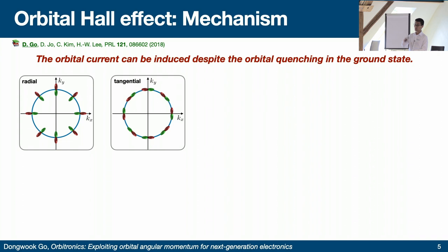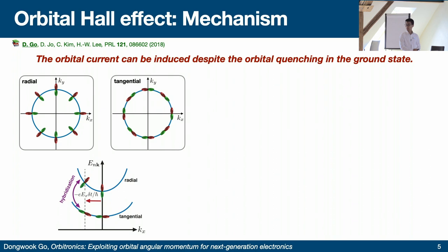The main starting point was that when there is a crystal field, it does not simply split orbitals in a rigid way. For px and py orbitals, the splitting depends on the crystal momentum k. Depending on the band, for p-orbital systems the orbital character in k-space can have either a radial texture or a tangential texture. But remember that these ground-state wave functions do not carry any angular momentum, because they are simply px or py orbitals — they are real functions with no angular momentum.